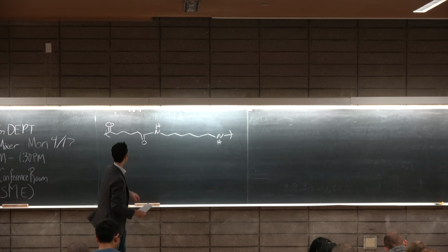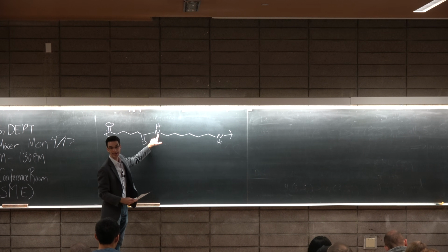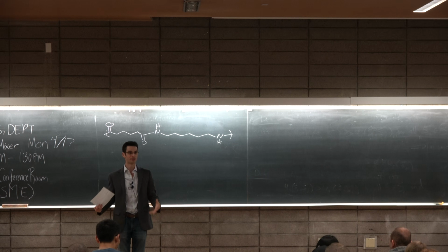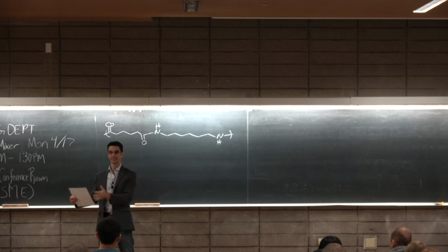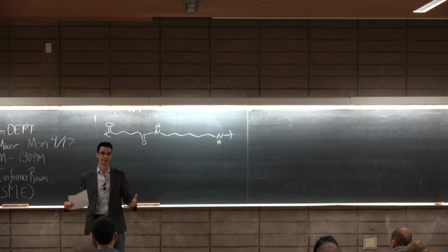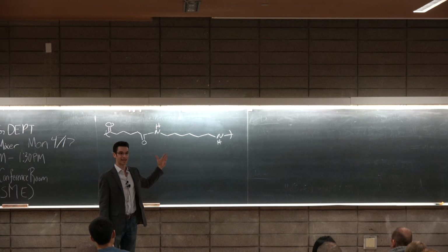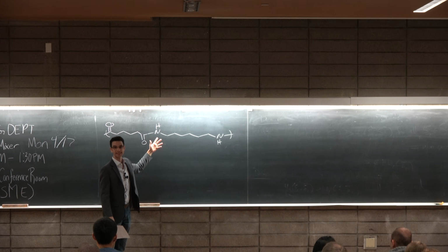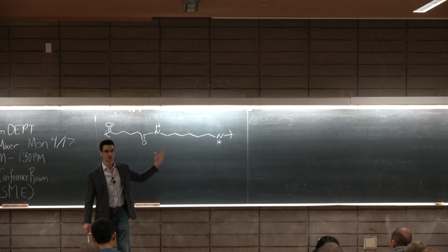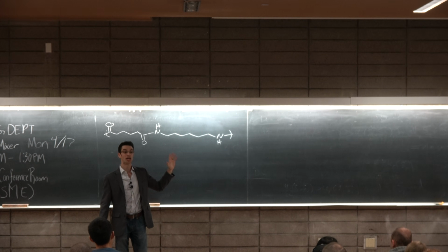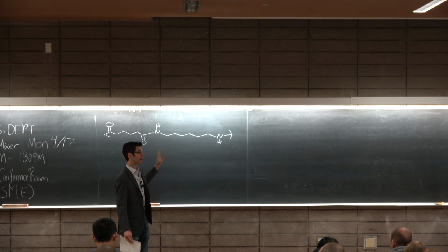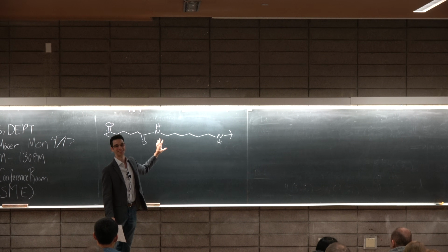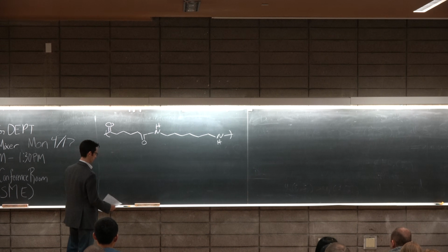You have this carbonyl and then this heteroatom next to the carbonyl, and this is just an artifact of the fact that you're starting with an acid or an acid chloride plus an amine or an alcohol to give you either an amide, as I've drawn, or an ester, which has the NH replaced with an O. So polyamides like nylon and polyesters are generally grown by step growth polymerization. Not always, but it's at least some forensic evidence that it may have been produced by a step growth polymerization.